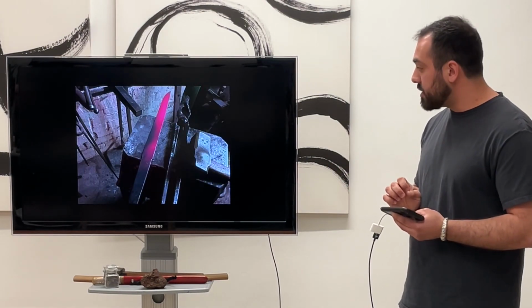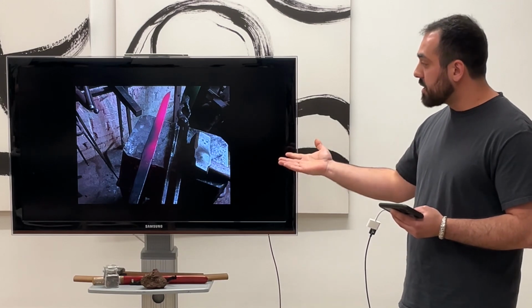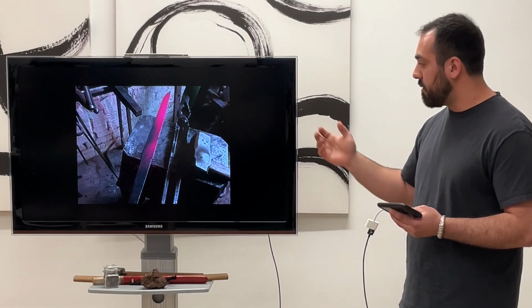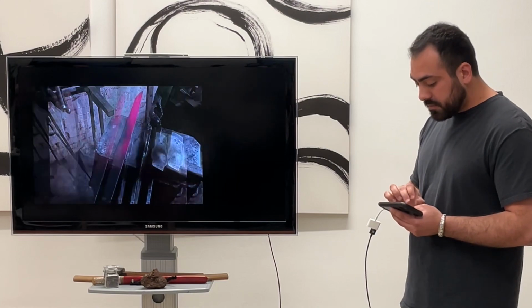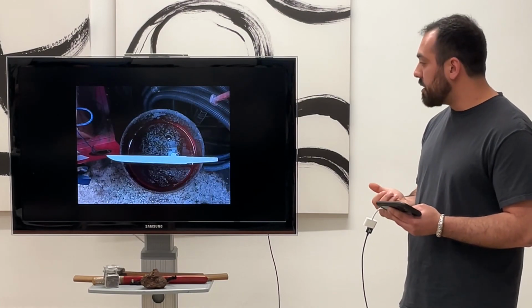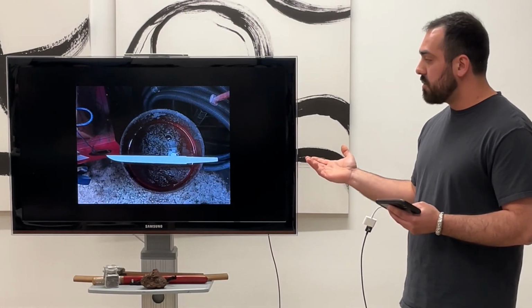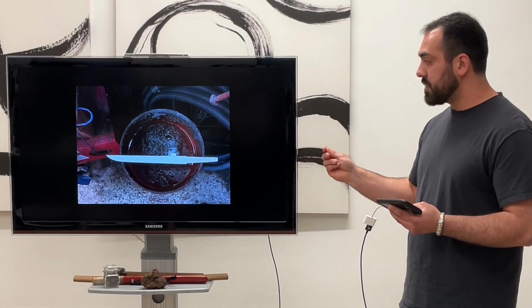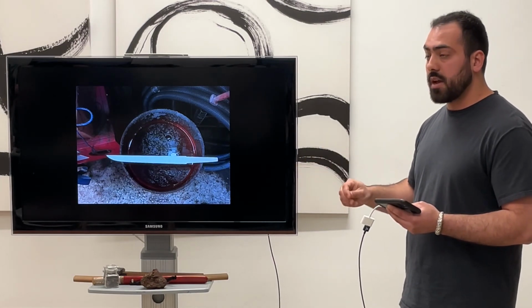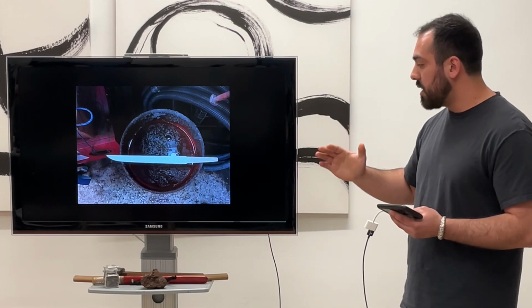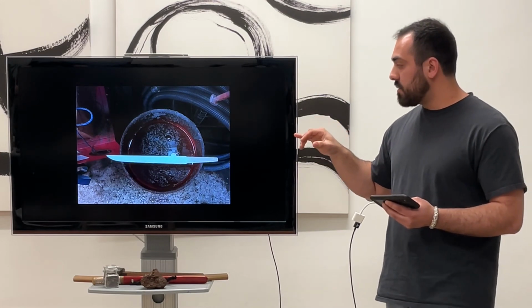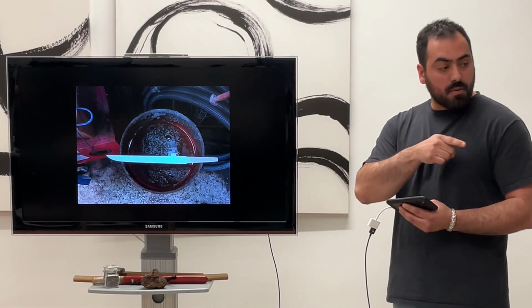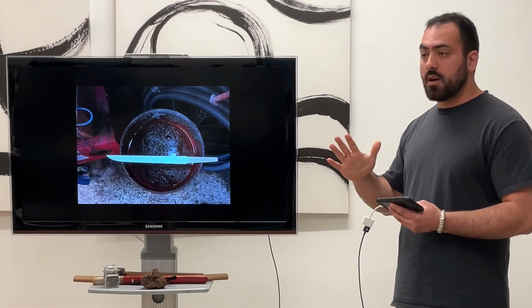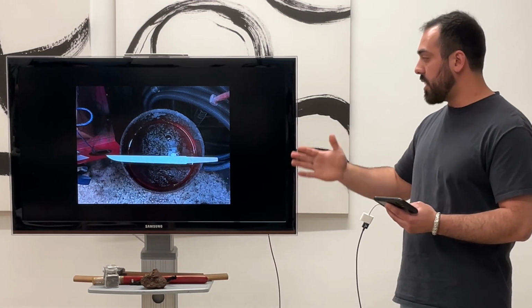Basically, after a little bit of forging, you end up with something that looks like a tanto, or a preform to one. And then you quench it in water. I cleaned it up with a grinder, kind of rough, just to get a clean surface so that I can go and affect the curvature of it. I didn't know to do this for a long time. Some of the pieces I brought with me have curvature in them, whereas I want the spine to be straight.